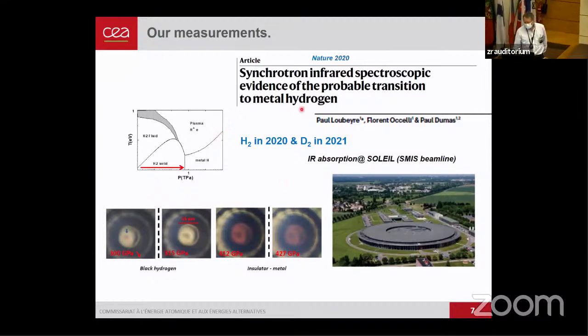And another experiment we performed at the beginning of this year on D2 showed the reproducibility, that we could do detailed measurements, and it really addresses the isotopic difference between these two samples. We performed the measurements at the synchrotron Soleil, which is in Orsay, France, on the infrared beamline, and roughly this is the kind of sample we observe there.